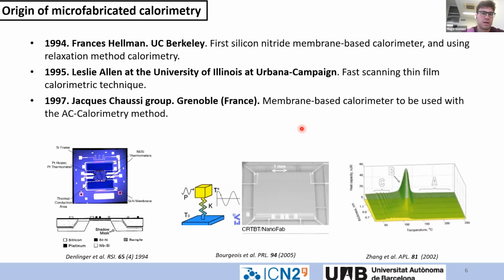The calorimeter that we are using started more or less in 1994 with the work of Frances Hellman from the University of California, Berkeley, with the first silicon nitride membrane-based calorimeters. This was also developed by Leslie Allen, the fast scanning thin film calorimetry technique, where we can have very high heating rates and also very high resolutions. And in 1997 in Grenoble, in France, membrane-based calorimetry was used with the AC calorimetry method. With this technique, we can reach a very high resolution, but the problem is that we cannot access very small areas, which is what we have in these 2D materials.